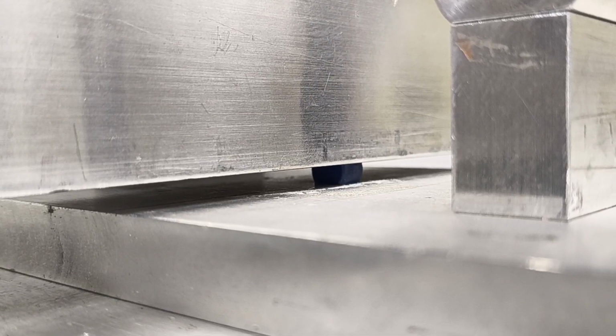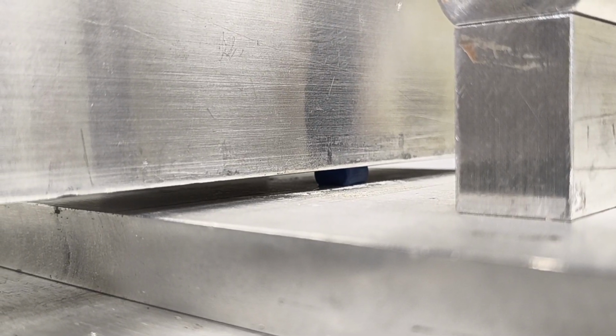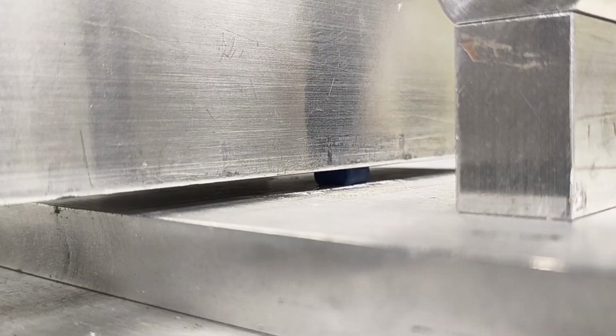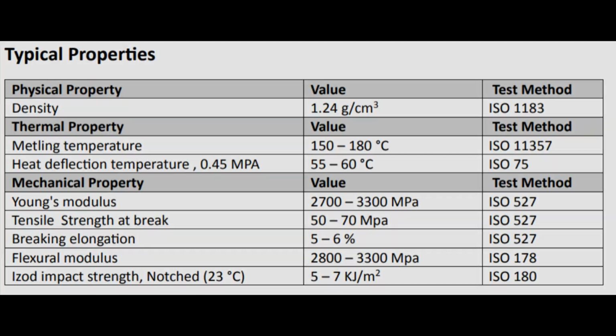A notable difference of our results in theory was the variance of data between our control sample and the manufacturer's data. The explanation for this is that Ziltech's data was gathered from samples in tension due to the ISO 527 test, rather than in compression such as we did.